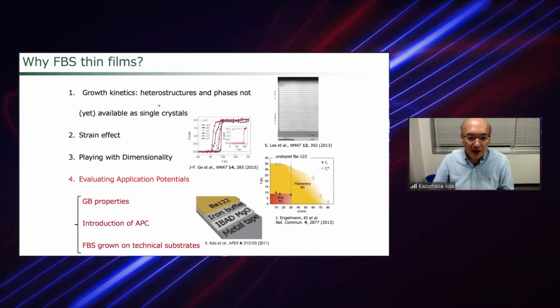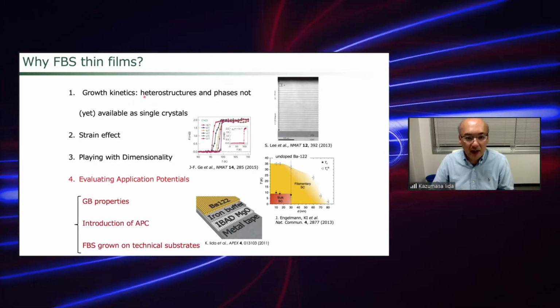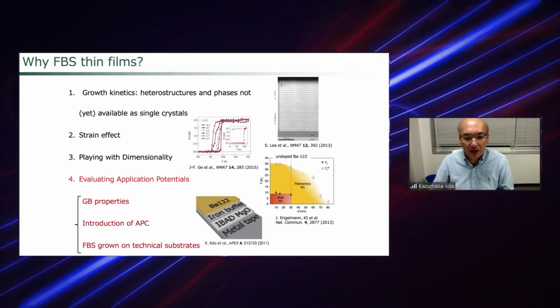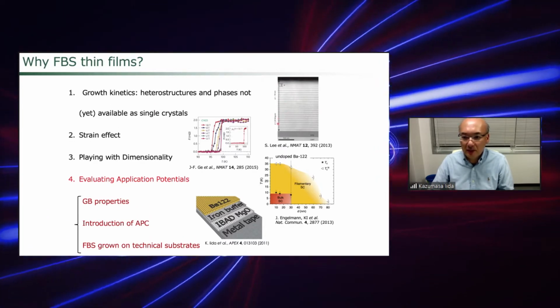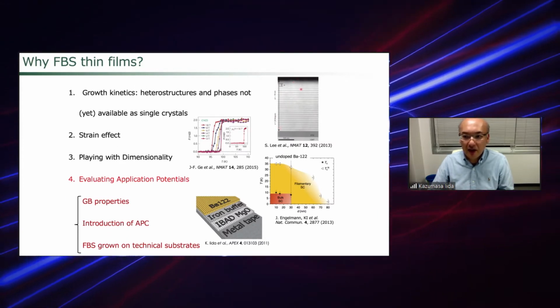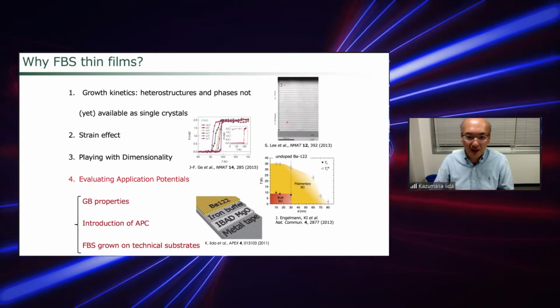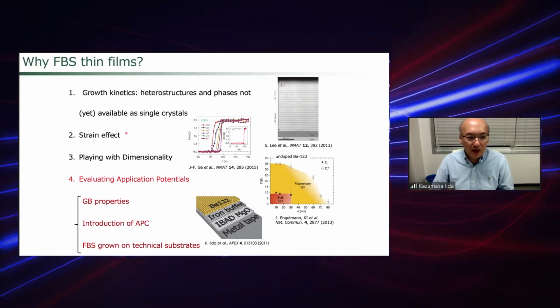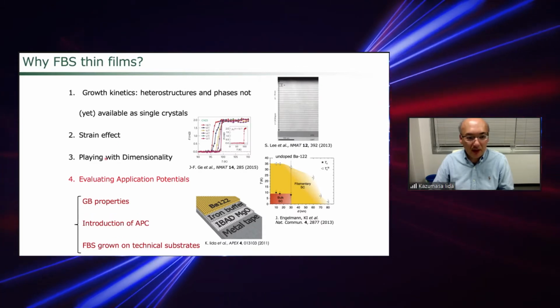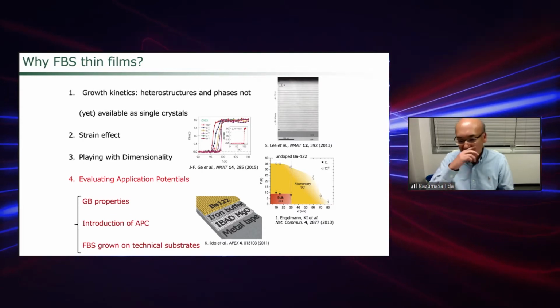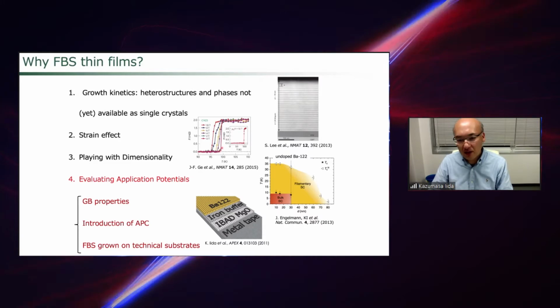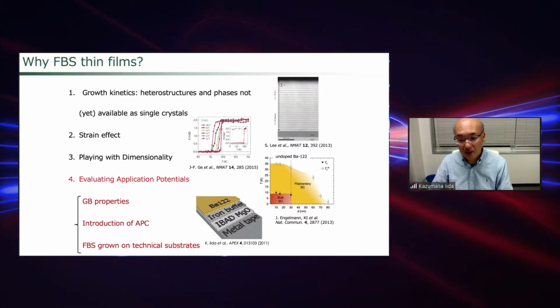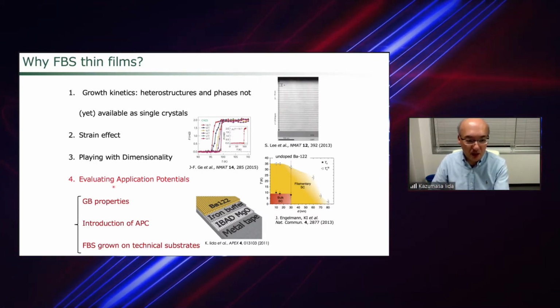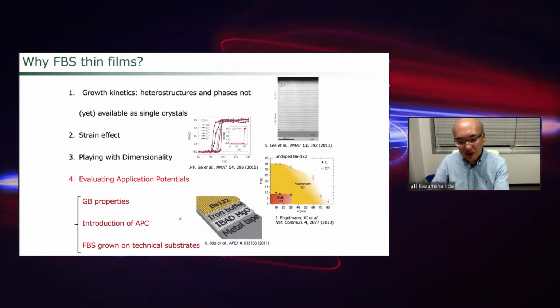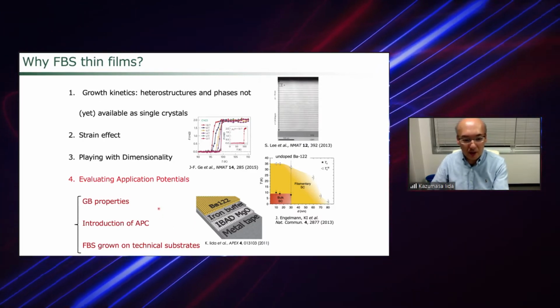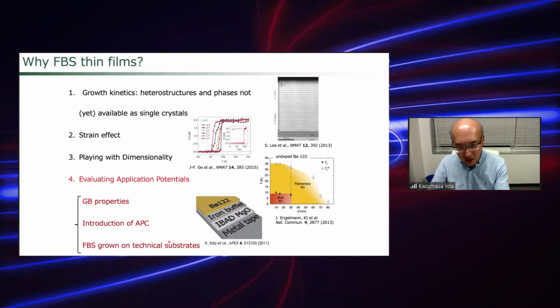So now we are interested in thin films. Why? Because there are several merits. One is that heterostructures and phases not yet available as single crystals can be fabricated. This is a good example of a superlattice of barium 122 and strontium titanate. These structures are not possible in nature. Also, it is possible to investigate the strain effect and to tune the dimensionality quite easily. This is an iron selenide monolayer grown on niobium-doped strontium titanate, and the Tc exceeds nearly 100 Kelvin. Most importantly, it is possible to evaluate application potential by conducting three kinds of experiments. So in this talk, I will briefly talk about each topic in the following presentations.